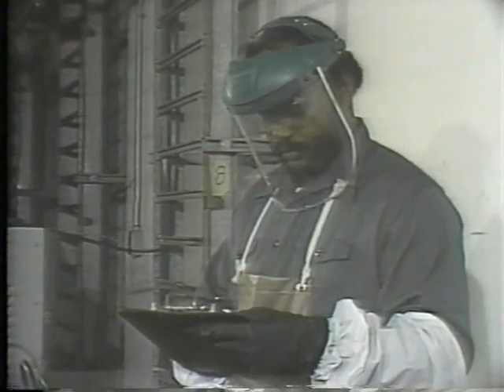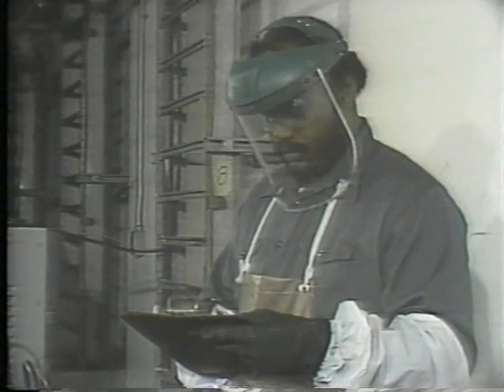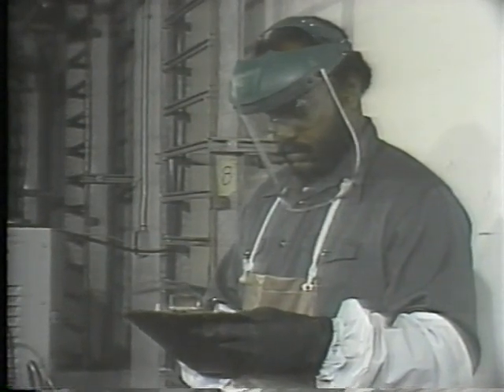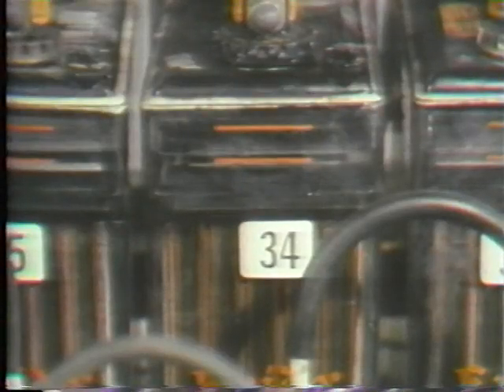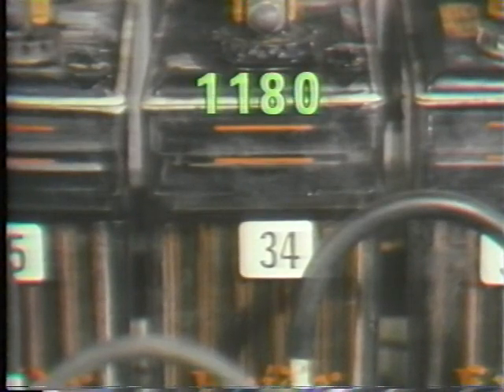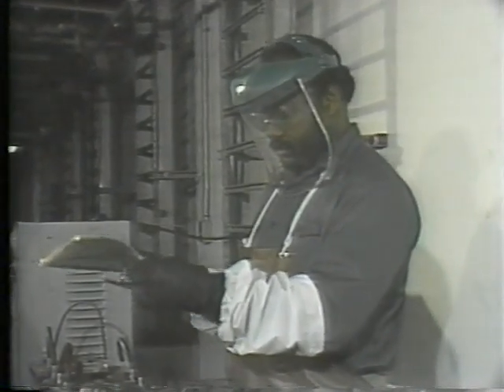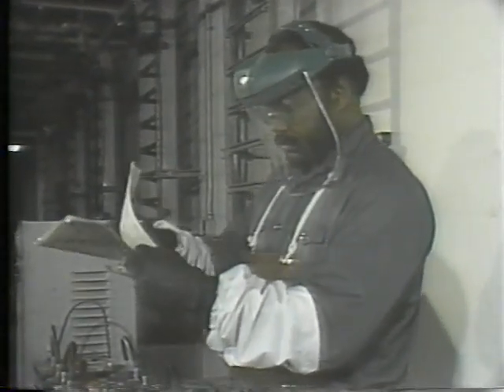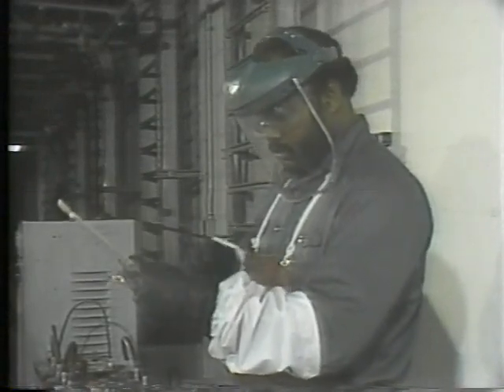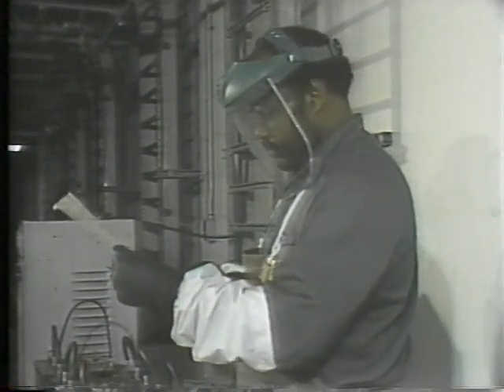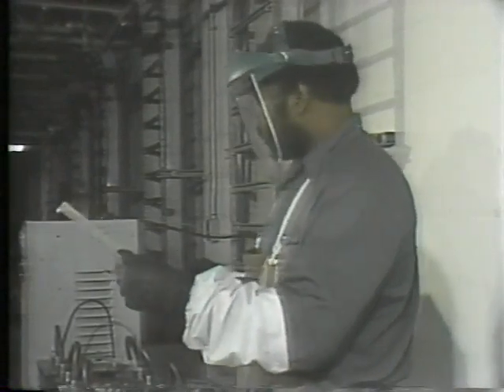After all the readings have been corrected, most of the cells seem to be within normal limits, except for cell number 34. A specific gravity of 1.180 is far below normal. Looking back over the last half dozen hydrometer checks shows that a trend has been developing. Specific gravity for cell number 34 has been steadily declining over the last few months. There are several possible reasons for the cell's low state of charge, but there's one simple corrective action that might take care of the problem.